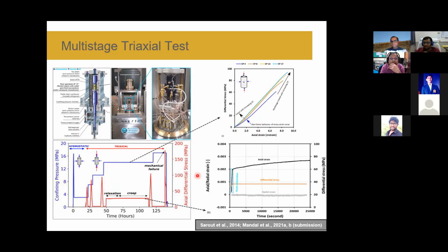And this section is basically showing this creep response, a little bit zoomed version itself. Here I forgot to tell you that during this deformation, we measure the deformation along the axial direction. You can see these two LVDT panels, which measure axial deformation, and we can also measure the radial deformation. There is a radial cantilever here as well, so we can measure radial strain as well as axial strain.